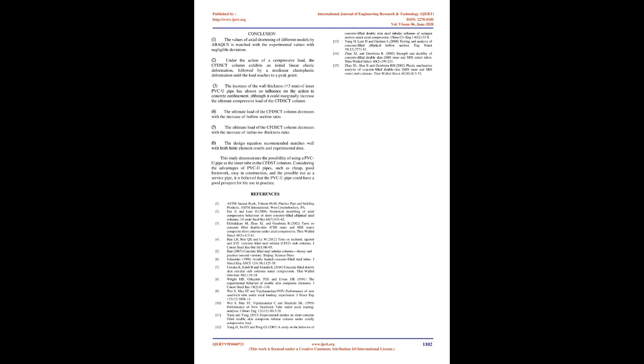3. The increase of the wall thickness, greater than 3 mm, of inner PVC-U pipe has almost no influence on the action of concrete confinement, although it could marginally increase the ultimate compressive load of the CFDSCT column. 4. The ultimate load of the CFDSCT column decreases with the increase of hollow section ratio. 5. The ultimate load of the CFDSCT column decreases with the increase of radius to thickness ratio. 6. The design equation recommended matches well with both finite element results and experimental data.